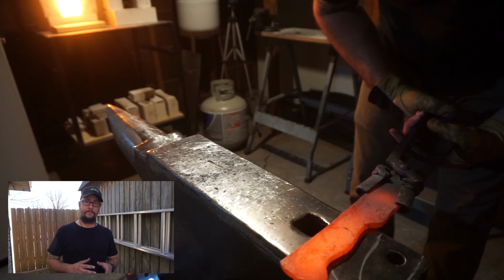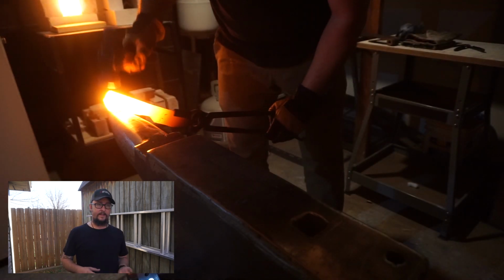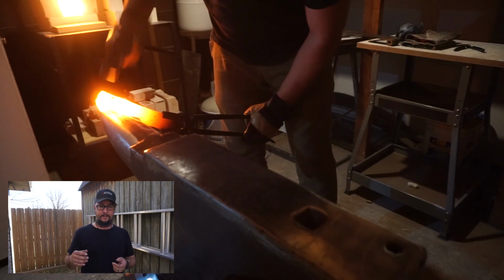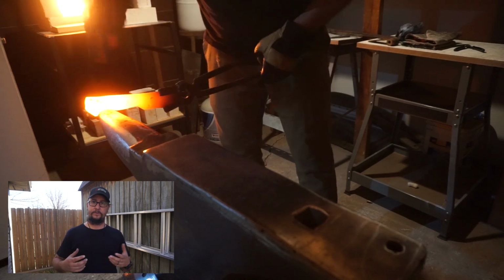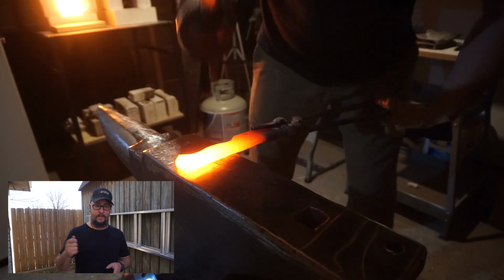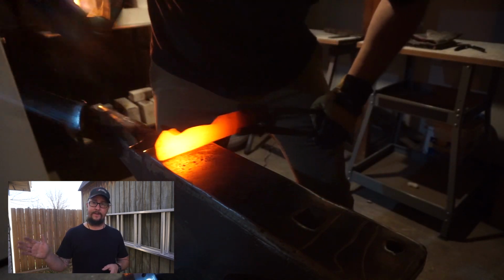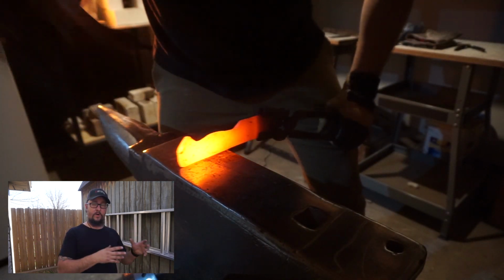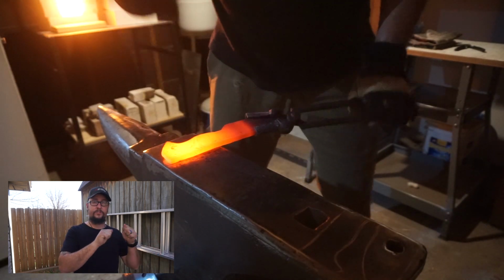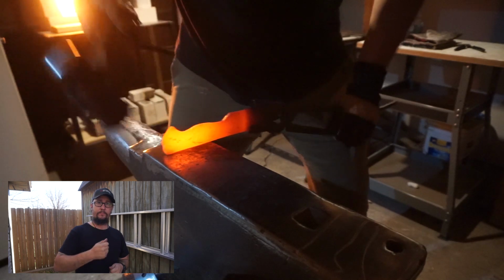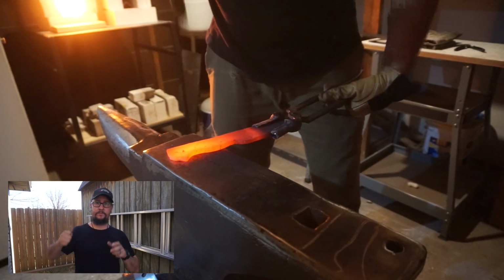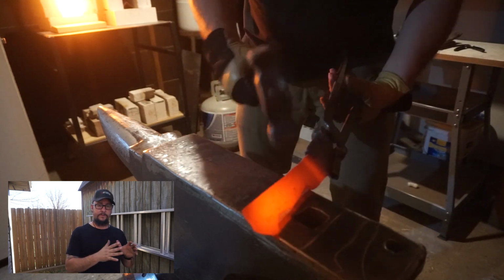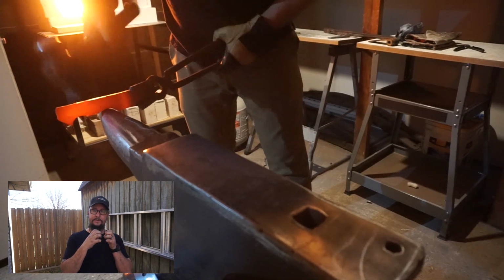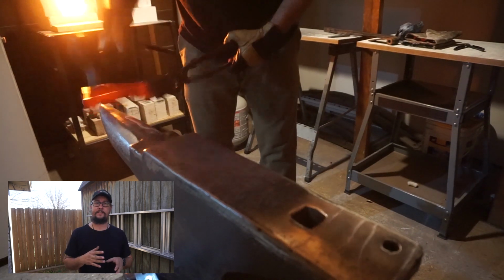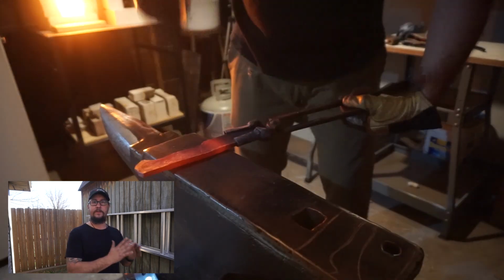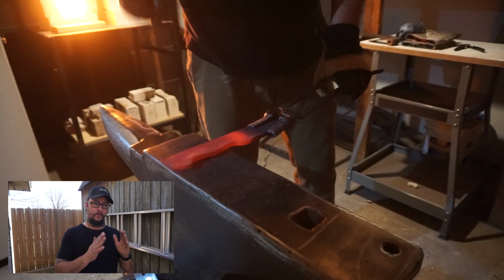Because if you do not temper it, you are going to have something that might be around that 65 Rockwell, and it's going to be as brittle as a file. If you just took a file right now and dropped it on concrete, there's a good chance that that file is going to snap in half. It's so hard that it can cut steel, but it's too hard to be a tool that you would chop with or slice with or flex or anything like that. So what you do is you temper that hardness back a little bit so that you have something that is usable but can still keep an edge. And that's why we're going for that straw color.